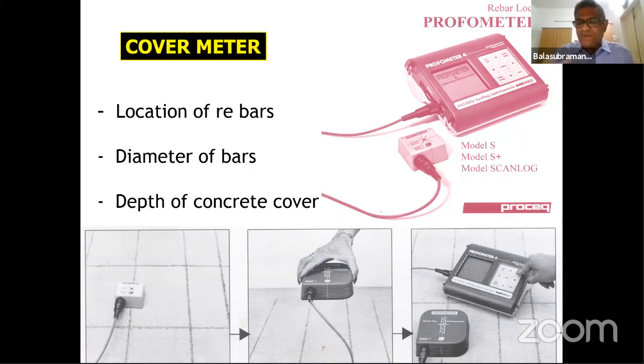And whenever we do work for some of the IIT professors, particularly for the design check where the GFC drawings are not available, we do the profoscope survey in a number of locations. And then what we do is randomly chip open after taking permission from the owner. We chip it open and cross-verify the profoscope, because this profoscope may have an error of plus or minus 25%. So you need to be very careful in predicting the diameter. You should not give the designer wrong numbers. Suppose there are 10 stories and you're doing a profoscope at about 80, 90 locations. At least in 5-6 locations, you can chip open and cross-verify the profoscope or profometer prediction of the diameter with the actual bar.